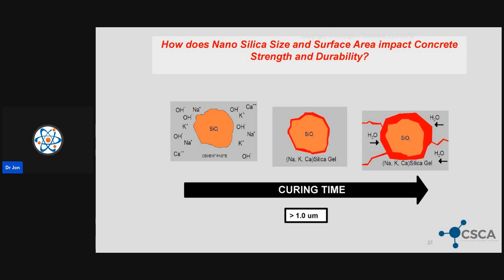And as it turns out, with the smallest particles, and you can go back to a lot of the research, not only the research that we've done, but a lot of folks from other universities from all over the world, show that those particles that are really, really small have a tendency of burning up faster and getting lost in the hydrated product. And we have to question whether or not it's nanosilica anymore, or is it now chemically incorporated into the calcium silicate hydrate network.